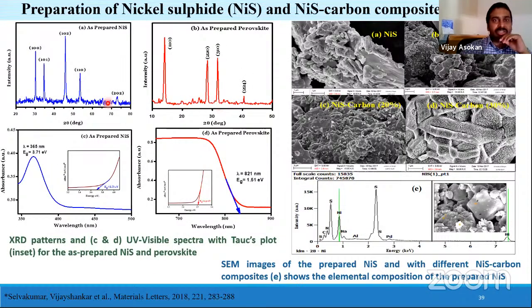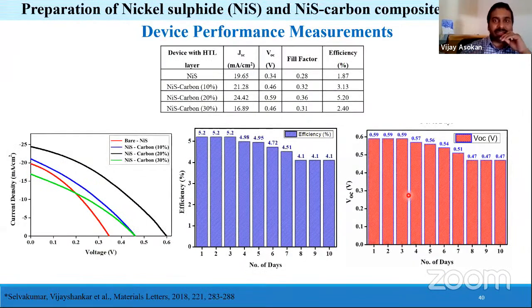So we have even checked with XRD and UV visible, and we even used BET to understand the surface area parameters. Then we calculated band gap of such materials using Tauc plots by taking UV visible spectra. And here are the nickel sulfide and carbon composites with different percentages of carbon within the composite, like 10, 20, and 30%. So these are the different combined materials we put into the device structures, and then calculated the efficiencies.